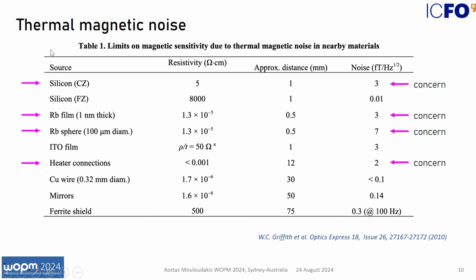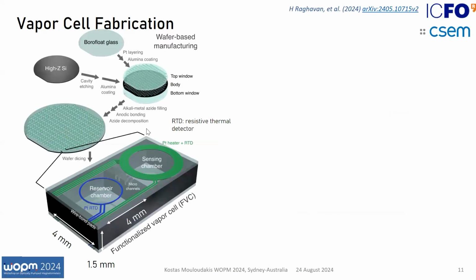And there are certain concerns regarding the resistivity of the silicon body, also the condensation of rubidium in the vapor cell on the glass, and some concerns regarding the heater connections and the heater traces. Keeping those things in mind, we decided to go with this dual vapor cell, dual chamber design, where it's a high-Z silicon body. Each chamber has a dimension of 4 by 4 by 1.5 millimeters, and we have microstructured thin film platinum traces deposited on the glass, which work both as heaters and as temperature detectors.